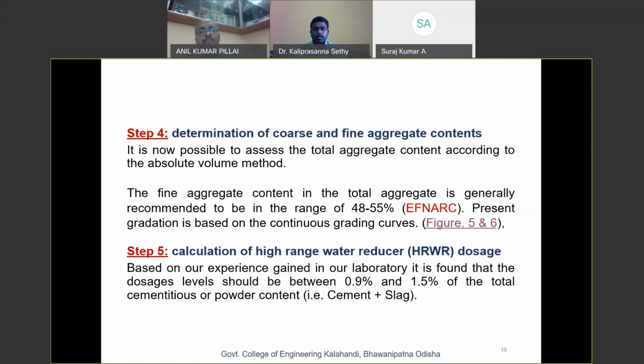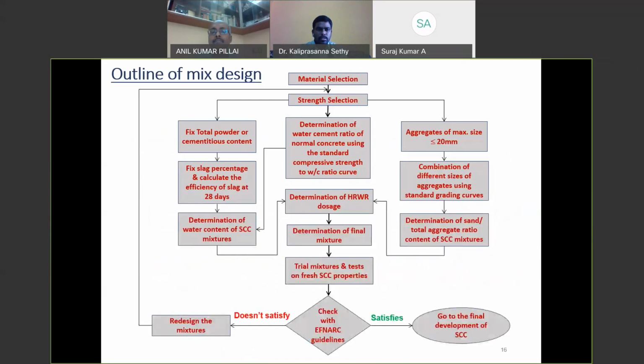After fixing all these materials for the development purpose, we have to select the superplasticizer, that is high range water reducer dosage. Based on experience, that is trial and error in our laboratory, we found that the dosage levels should be between 0.9 to 1.5% of the total cementitious powder content, that is cement plus slag, which are used here. And this is all about the mix details. Based on these mix details, we set the outlines, the flow chart of these mix details. We selected materials, checked for strength selection, fixed the total cementitious materials, and with these flow charts we came up with trial mixtures,